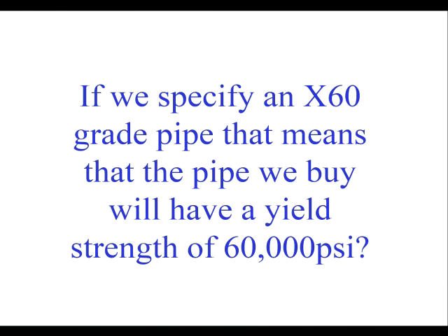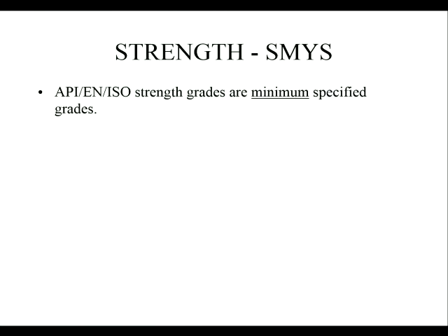So, if we specify an X60 grade pipe, that means the pipe will have a yield strength of 60,000 psi. Is that right? At least, is the simple. It should. So these are minimum specified grades. So just because it says X60 doesn't mean to say that a particular pipe from that run is actually X60. It means it's a minimum of X60. And you might find, if you did tests on individual pipes, that one pipe was X60, the next one was X65, the next one was X70, then we had another X60. So the pipeline strength can vary, but none of them will drop below 60,000.